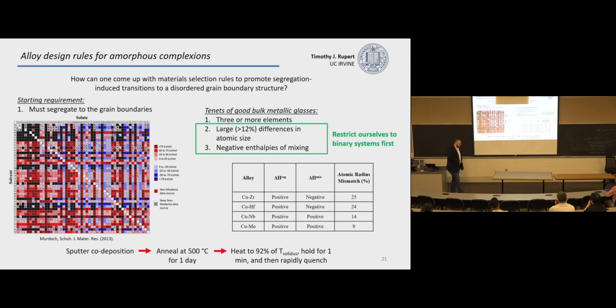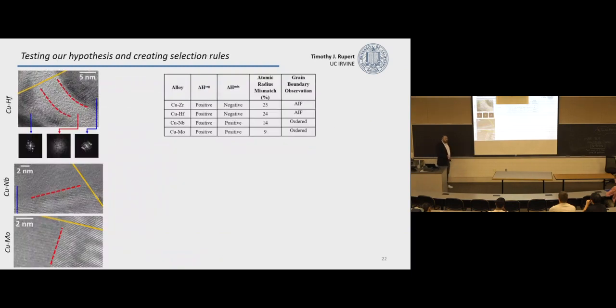Okay. We also wanted to see if this idea that we were studying in these mechanically alloyed materials was possible with other types of processing routes. So these were sputtered. We annealed at a lower temperature to allow for segregation. And then our idea was that if you have segregation, that local transformation at the boundary shouldn't take very long. So we do a really high temperature annealing, but only for a short period, only 1 minute. And we can go in, I already showed you copper zirconium has these features. We showed it for the sputtered films, but I'm not going to show it here.